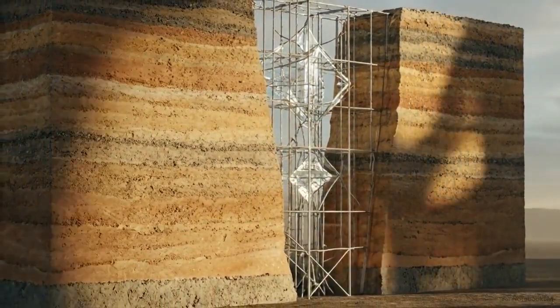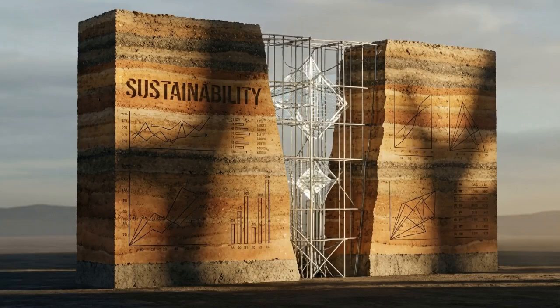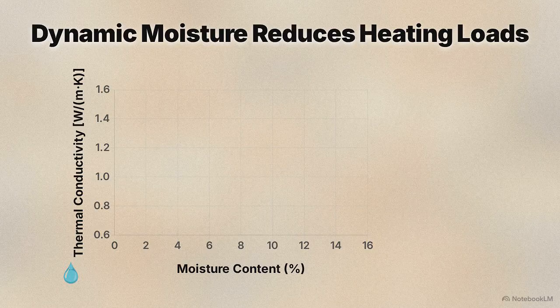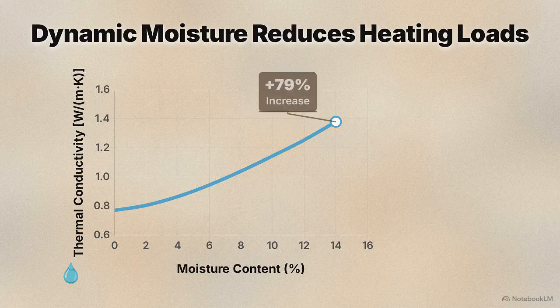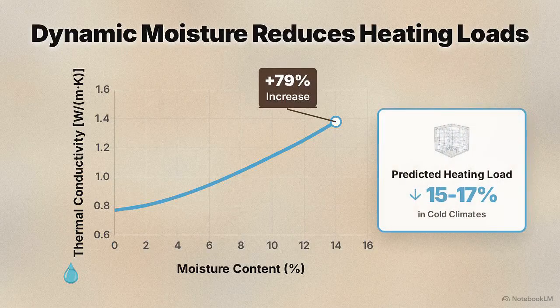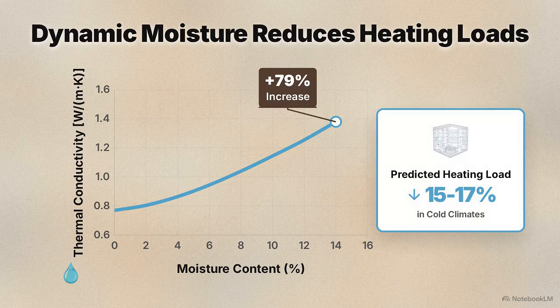material's actual performance metrics. A recent study published in China's Sustainability Journal finally quantified the precise hygrothermal relationship in earthen walls. This graph shows how sensitive the material is. As moisture increases to 14%, thermal conductivity rises sharply from 0.77 to 1.38, a 79% increase. When dynamic variables are engaged in simulation, predicted heating loads in cold climates drop by 15 to 17%.